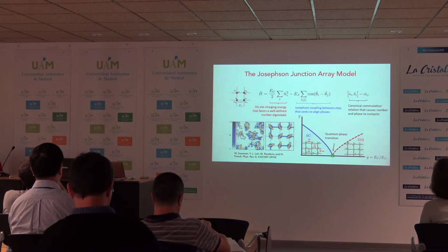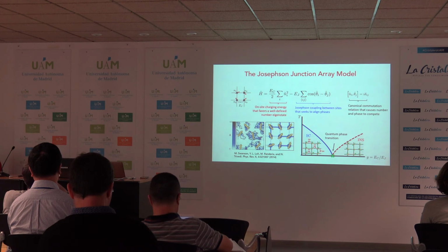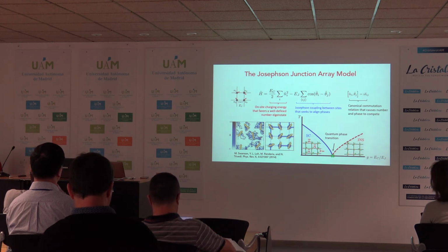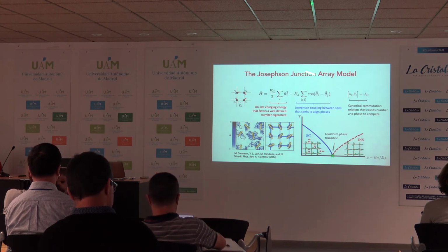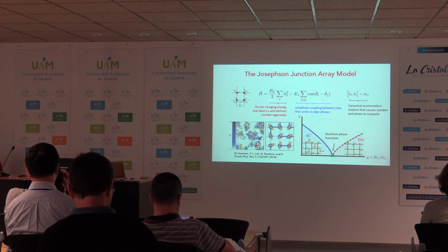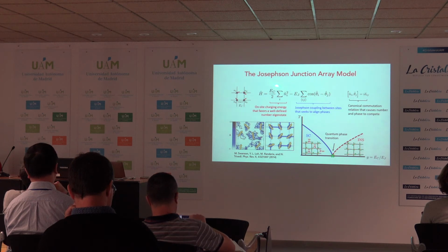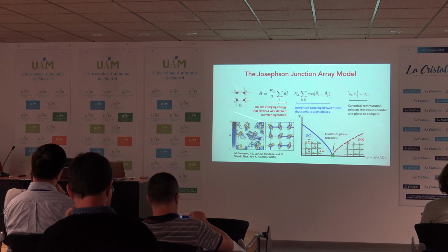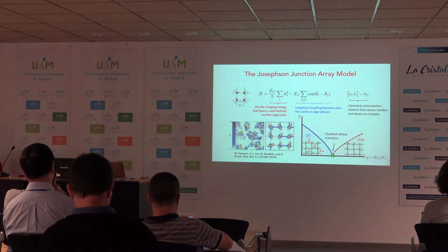I'm not going to go into this too much, but as we understand one level of the theory, we can start coarse graining. And now that we know we have these patches, and really the behavior near the transition is governed by phase fluctuations, we can start to build models of Josephson arrays, a quantum Josephson array model, where the patches become the sites of a two-dimensional network, and these phases are coupled through some Josephson energy, Ej. What competes with that are the number fluctuations. So there's a charging energy on each of these patches or grains, which has a strength EC, and because these two operators don't commute, that's what builds in the quantum fluctuations that drives this transition.